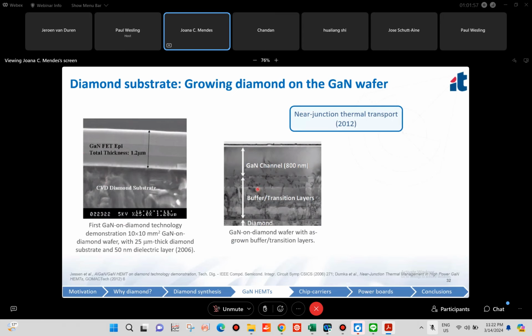But curiously, this structure didn't show any thermal benefit. Actually, it behaved even worse than, for instance, GaN on silicon carbide. And why is that? Because the hotspots are here on top of the channel.